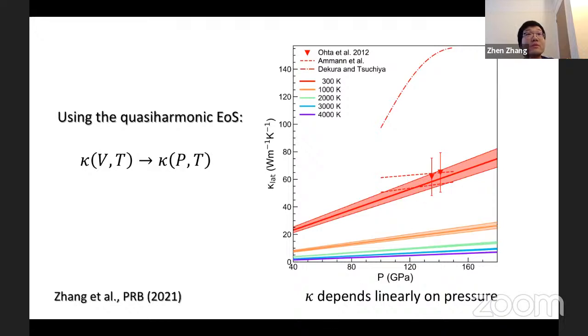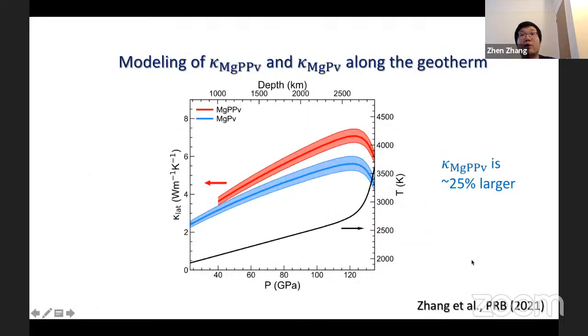With kappa of PT obtained, kappa of magnesium post-perovskite was modeled along the typical geotherm with a thermal boundary layer above the core-mantle boundary. It was compared to that of magnesium perovskite. We found that in the D double prime region below 2,600 kilometers, magnesium post-perovskite kappa is around 25% larger than that of magnesium perovskite.